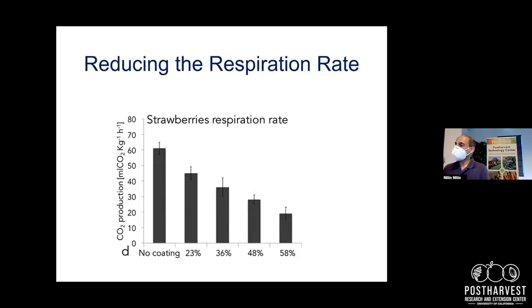And remarkably, they also showed that using high beta sheet content in silk, they were able to depress the respiration rate. So the strawberry respiration rate was significantly reduced as the beta sheet content of the protein increased. And again, you can compare that to without coating, which is significantly larger. So it's about a 3 to 4-fold slower respiration rate over a period of time.